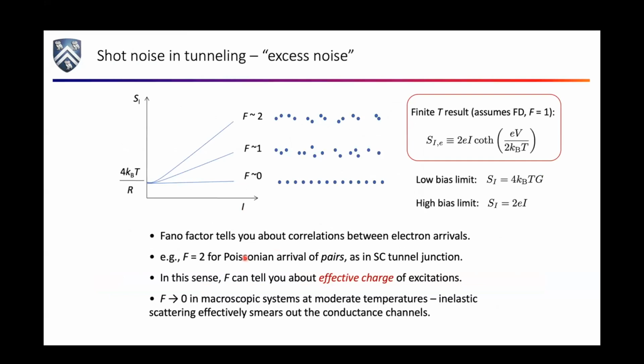So if you do this in tunneling, where you're adding and removing whole charges, you can do a little bit better than this. First of all, there's a way to deal with the crossover between the purely equilibrium thermal noise at zero current and what's going on at finite currents. This is the nice expression for Fermi-Dirac statistics, with a quantum factor of coth. In the low bias limit, it gives you the Johnson noise, and in the high bias limit, it gives you the Poissonian result. And you can imagine a situation where you could get deviations from the Poissonian result, right?